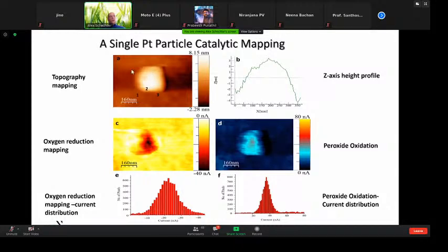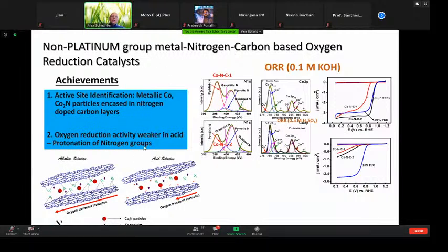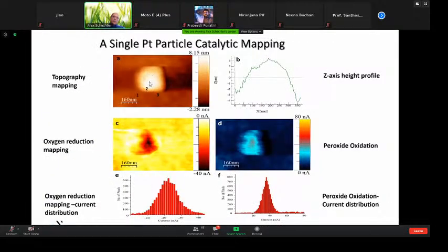This is on a single particle of a size of 160 nanometers. This is a platinum particle. And you can see that most of the current is coming from the center, and you can see the peroxide is smeared all over that. So the resolution with peroxide follows to some extent that of the oxygen reduction, but not entirely. And the reason is, again, because it's done in two different reactions, two different experiments.